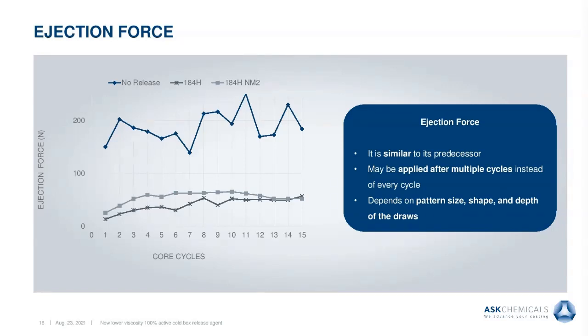The ejection force of the new lower viscosity release agent 184H NM2 was compared to its predecessor 184H, as well as to no release using the RTR equipment. The lower the ejection force, the better the release agent performance. The ejection force was measured over 15 cycles. The top line shows no release, where the ejection force is high and ranges from 139 to 250 newtons. NM2 release force ranges from 25 to 52, and 184H release from 13 to 56 newtons. NM2 and 184H release force is similar and on the low end, indicating that they may be applied after multiple cycles instead of every cycle.